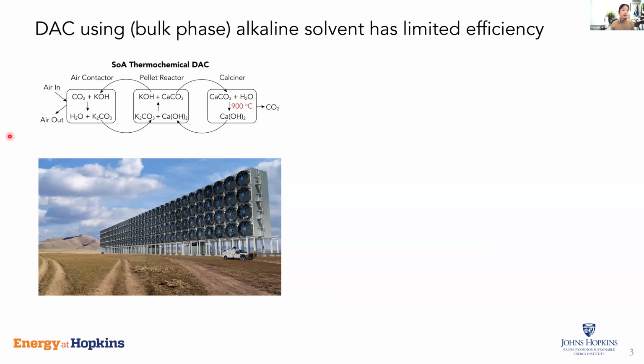The most mature method for direct air capture currently is to use a bulk phase alkaline solvent. The reaction is pretty straightforward. Usually we'll use an aqueous solution of alkaline, in this case, potassium hydroxide, and then we'll send it through a large air contactor to blow air through the bulk solvent and to promote the acid-base reaction between carbon dioxide and potassium hydroxide and form potassium carbonate.